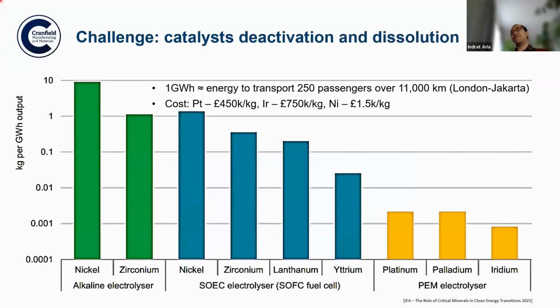And to make it worse, if we go with nickel or cobalt or iron, there is what we call materials consumption. The catalyst gets deactivated or dissolved over time when we use it for an electrolyzer or fuel cell. As an example, the y-axis there is the amount of material consumed in kilograms per gigawatt hour output for electrolysis, and the x-axis shows different types of materials. To give an example, 1 gigawatt hour is the energy required for a mid-size airplane to transport 250 passengers from London to Jakarta. So if we use nickel as a catalyst, we will consume 10 kilograms of nickel just for one medium-sized airplane flight from London to Jakarta.